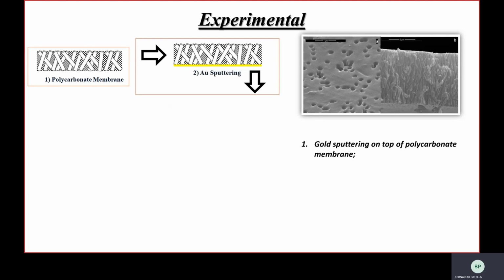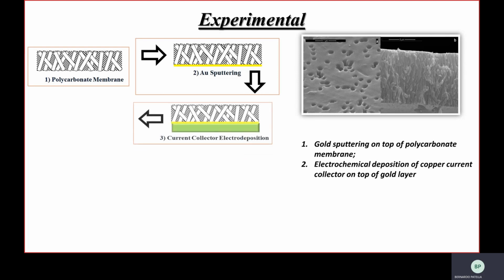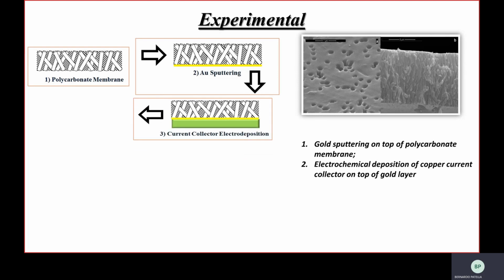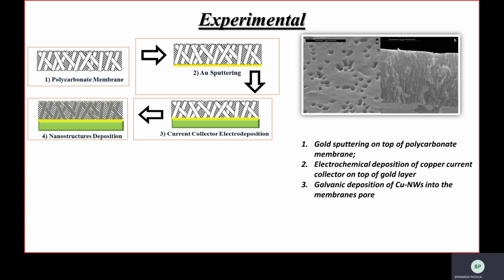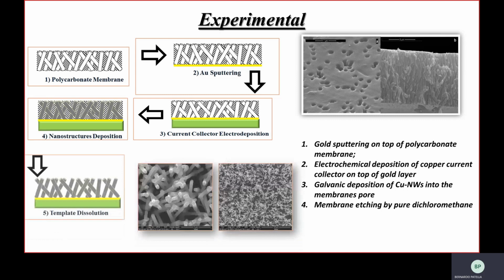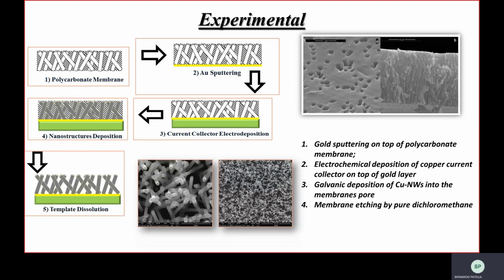In order to make the membrane conductive, it was sputtered with a thin layer of gold, and subsequently, a copper current collector was deposited by electrodeposition on top of the gold film. The current collector was then coupled with an aluminum tube and immersed into a solution made of copper cations. In this way, the aluminum dissolution produced electrons that reduce the copper cations to metallic copper directly into the membrane's pores. Finally, the membrane was etched by pure dichloromethane, and an electrode made of vertically standing nanowires was obtained, and the nanowires are perfectly anchored to the copper current collector.